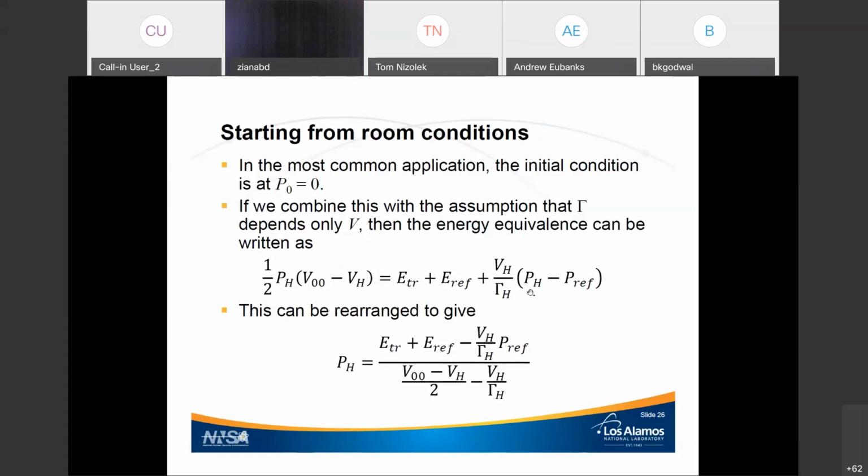So if we have some equation of state with, say, a Mie-Grüneisen temperature or energy dependence as a function of volume and some reference compression curve, we can calculate a point on the Hugoniot for any given Hugoniot volume and starting phase from that equation of state, making the assumptions that the Hugoniot state is in equilibrium and the situation is hydrostatic.